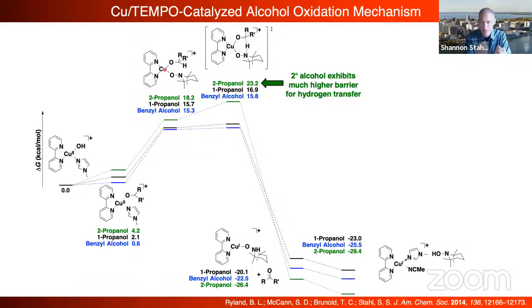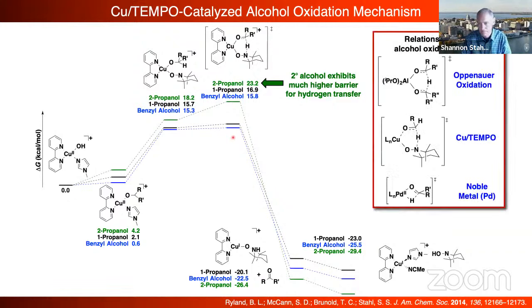That makes sense because TEMPO is a mild oxidant, right? We often use it as a mild oxidant or an HAT reagent. Ligands are supposed to be electron rich, right? The reason they bind to metals is because they've got electron density that binds. Well, TEMPO is an oxidant. It doesn't want to bind to copper. And so the major barrier here is actually getting TEMPO on. And then you can see transferring the hydride is almost barrierless when you don't have steric effects in this chemistry.